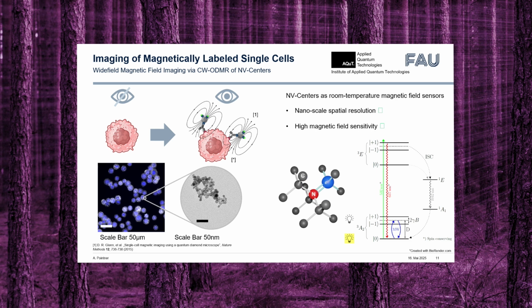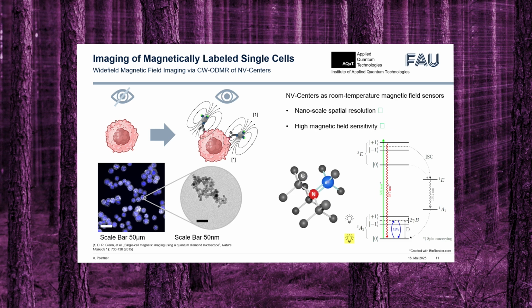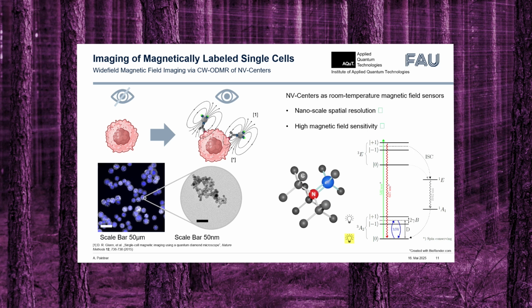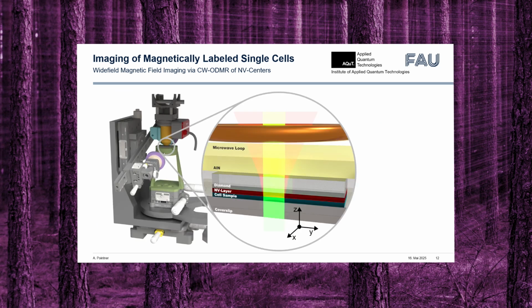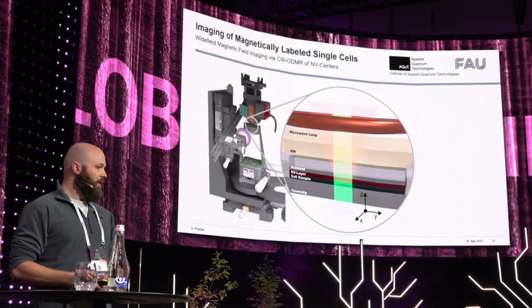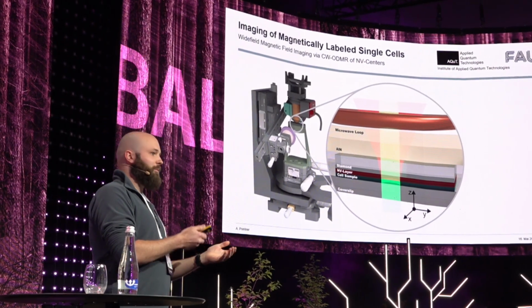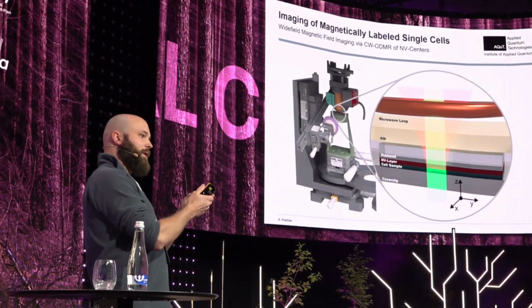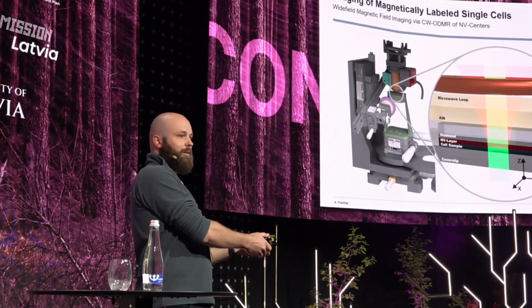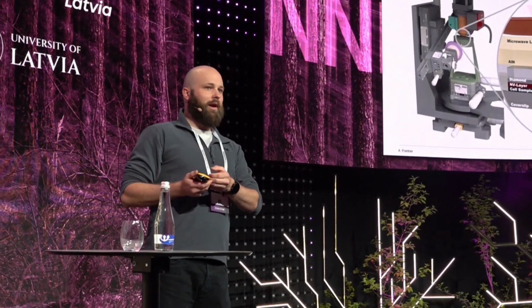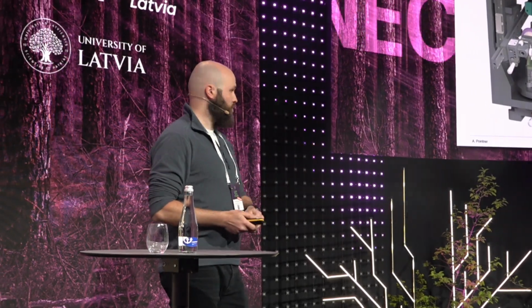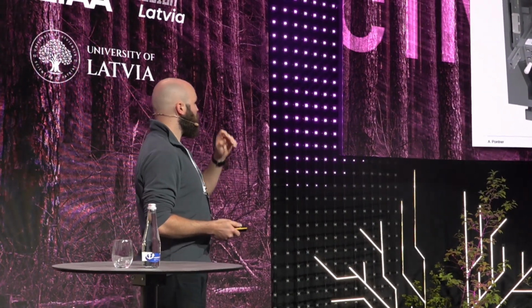And it offers the high magnetic field sensitivity that is required in order to resolve this faint magnetic field caused by these magnetic markers. So what we need at the end of the day is a magnetic microscope, and this is what we've built. We use the diamond as a mediator between the magnetic signal from the label and the optical domain that allows us this microscopic resolution. And this is something that we've built up.